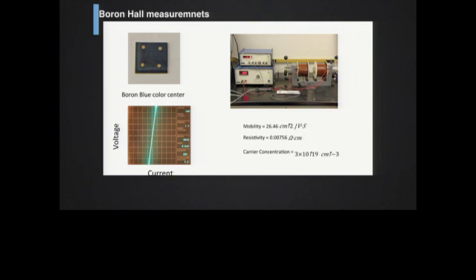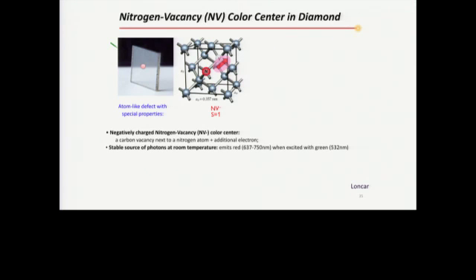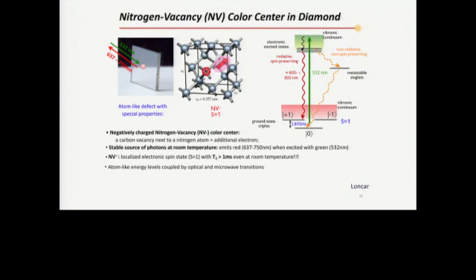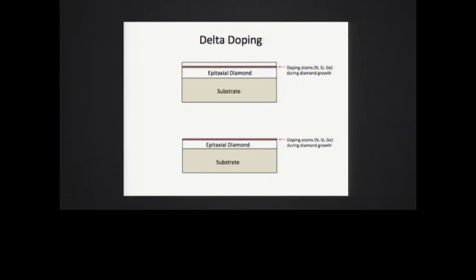With this solid source technique, we don't have a whole lot of variation in the doping concentration because it's hard to set the vapor pressure of the boron. Of course, this is a famous nitrogen vacancy center here. I'll just quickly go over that, skip that.